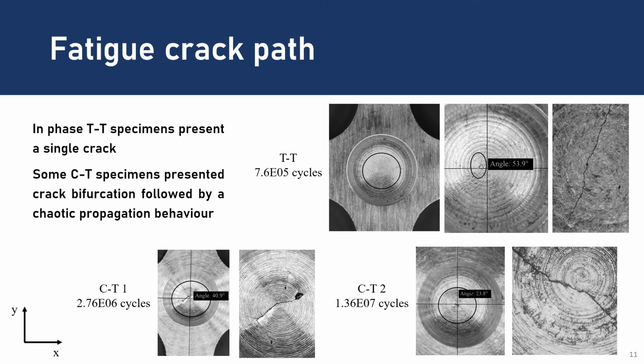Now, comparing TT and CT specimens, all TT specimens presented a single crack propagation, here with roughly 54 degrees of crack initiation, while the CT specimens presented both single cracks and cracks with bifurcation behavior. The bifurcation behavior started mainly at higher angles of crack initiation, where there is a small crack propagation followed by bifurcation. After some propagation of the bifurcation behavior, there is a chaotic behavior until the highest cross-section area. In single propagation CT specimens, the crack initiation angle is smaller, here around 24 degrees, and it follows roughly this behavior here drawn.